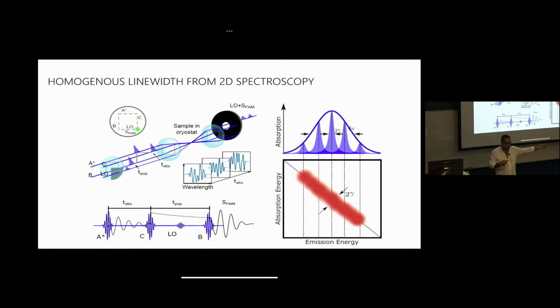So you Fourier transform that, and now you've got a two-dimensional spectrum of, let's say, an excitation axis, that's this, and a detection axis, what you measure at the end, okay? So you don't have amplitude versus energy, you've got amplitude versus energy versus energy. But these two energy axes, because it's a coherent experiment, contain correlations. Exciton A and exciton B are correlated. There should be a cross peak between these two energies. So that's an important thing that I'm going to show you in a minute.